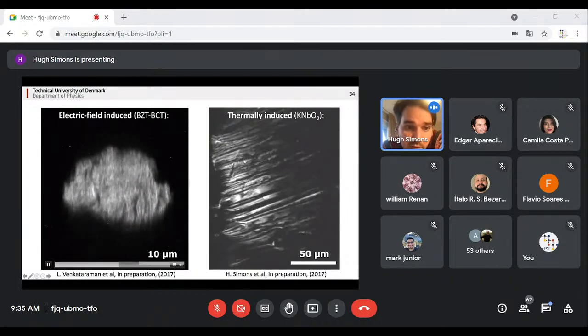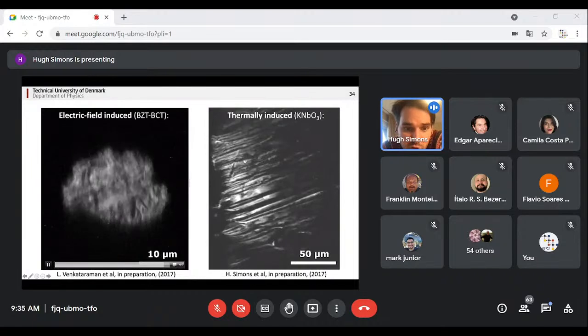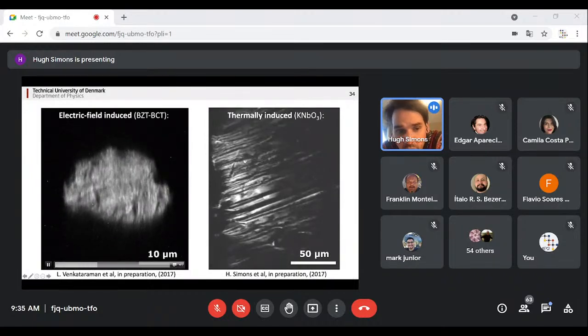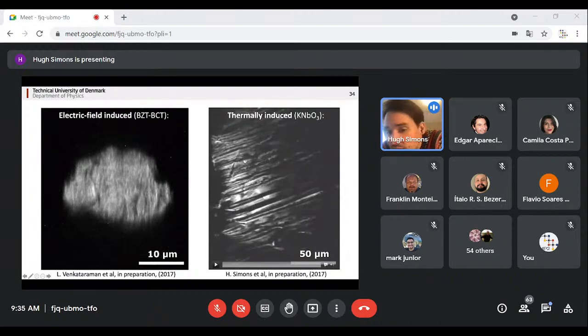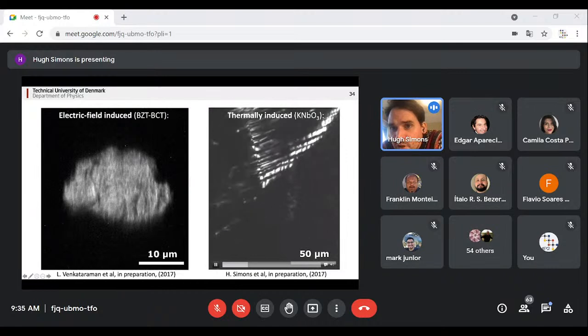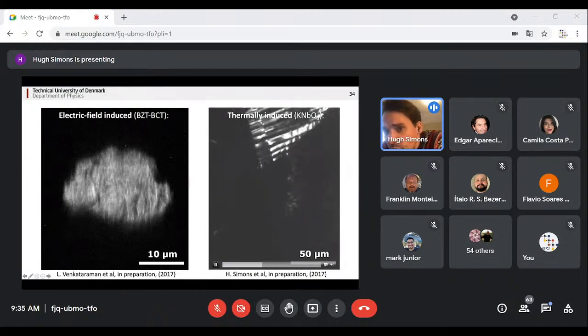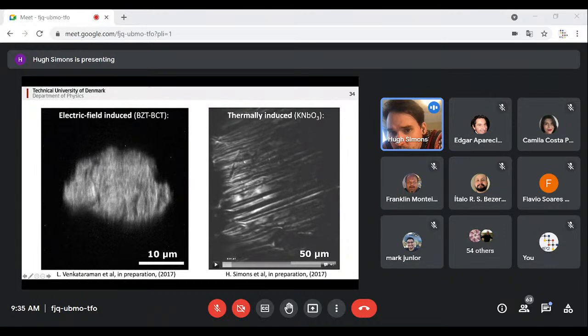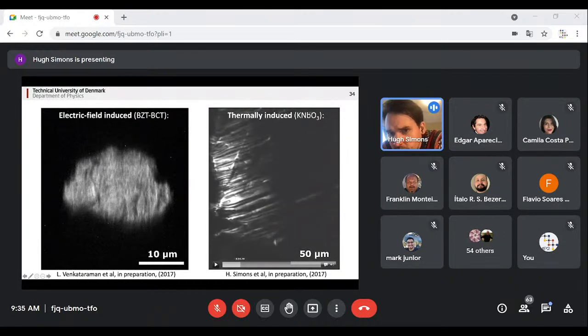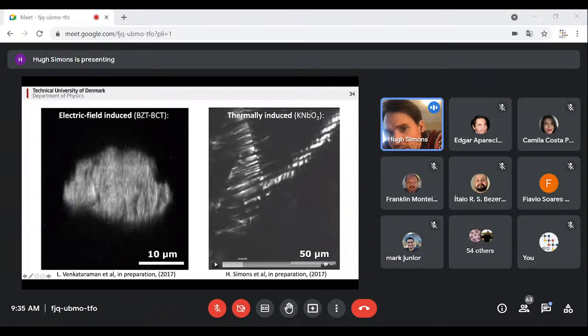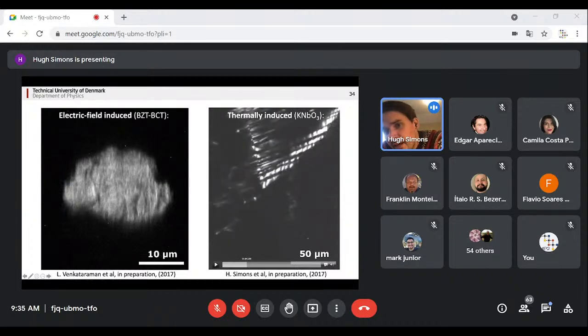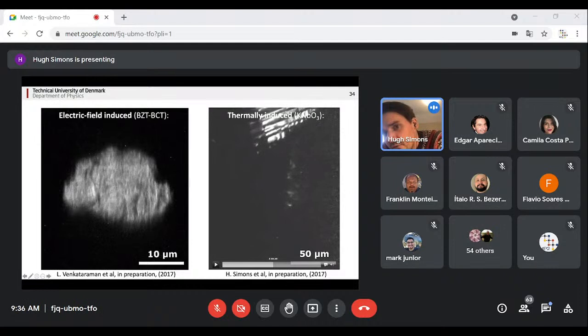So as we apply an electric field and release it, you see the structure change and new domain walls form and disappear. And in a more classic ferroelectric, potassium niobate, you can also see new domains form in this thermally induced phase transition. So if we rewind a little bit, you can see exactly at this point, new domain walls form at oblique angles. And as we heat up, these begin to proliferate through the sample.